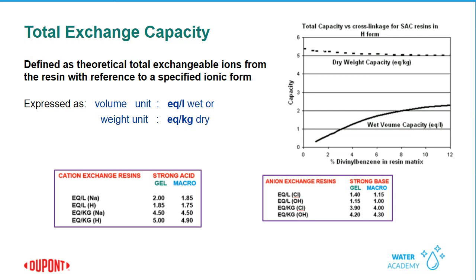Also, I wanted to point out with strong acid cation resins, as you increase in the percent DVB, remember that's our cross-linker that we're using for our styrene DVB resins. As you increase in percent DVB, you're going to get an increase in the wet volume capacity of the resin, or the equivalents per liter of the resin.